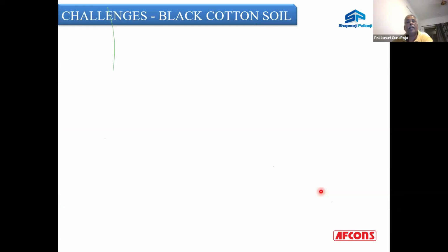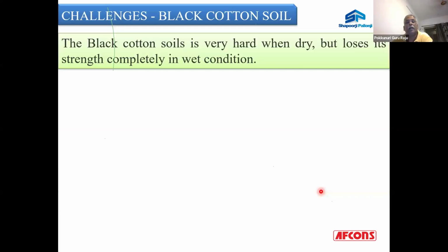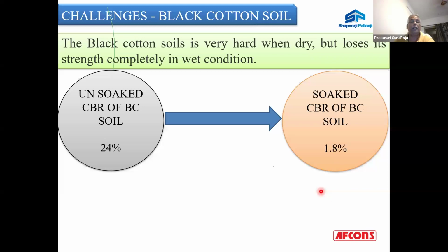Now, what exactly is the challenge in the case of a BC soil? Black cotton soil is very hard when dry, but it loses its strength completely in the wet condition. If you test the unsoaked CBR of the BC soil, it is in the range of 24%, for a sample which has a free swelling index of 70 to 75%. When the same sample is tested for 4 days soaked CBR in laboratory conditions, the CBR value is 1.8%. That means the same soil, which generally has a CBR of 24%, drops to 1.8% the moment it gets in contact with water.